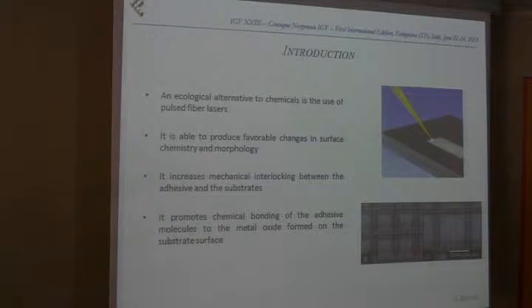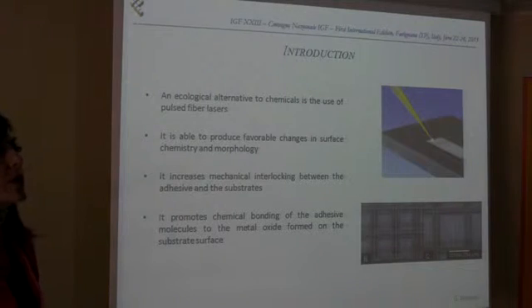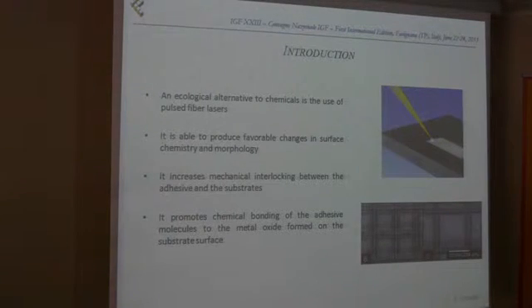which has been also demonstrated to be effective as chemical treatments in modifying both the surface topography and sometimes the chemistry of the material. In fact, for some metals, it's been demonstrated that also laser pretreatment can modify slightly the chemistry of the surface treated by the formation of oxides, which are mating the adhesive and are resulting in a strengthening of the joint.